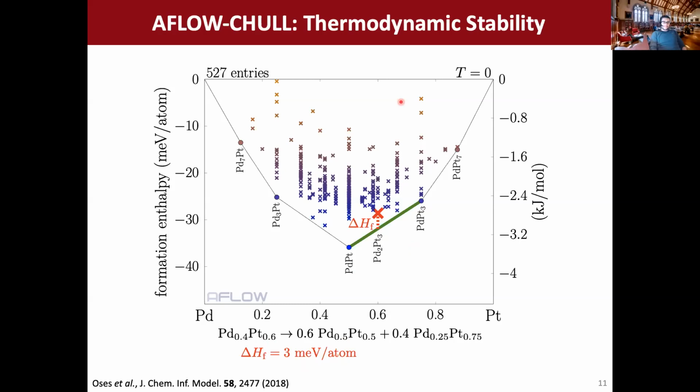Now remember, keep in mind that these calculations were done at 0 temperature and 0 pressure. So if we're interested in looking for materials at, say, room temperature and standard temperature and pressure, then we're not only going to want to look at the points that define the ground state systems, but also points nearby. So we might account for the thermal energy, or room temperature energy. This is about 25 meV. You can think of this as kind of an error to our plot. The point is that if we're looking for points that are stable and should exist experimentally, then we shouldn't only look at the ground state systems as defined by 0 temperature, 0 pressure, but also those that are nearby, maybe to within 25 meV or a little more.